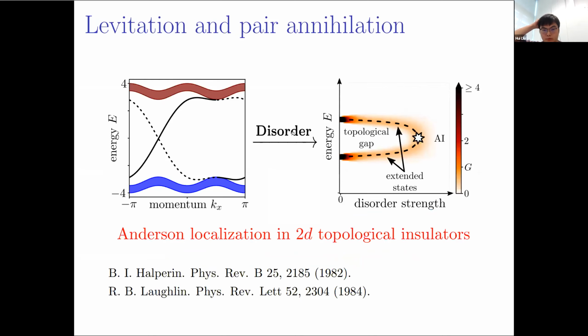Now, when we introduce the disorder into this system, this non-trivial band would be split into two parts. The first part in the margin of the band corresponds to the localized states, which do not contribute to conductance. The second part in the middle of the band is for the extended states. These extended states carrying inherent non-zero topological invariance and contribute to conductance.